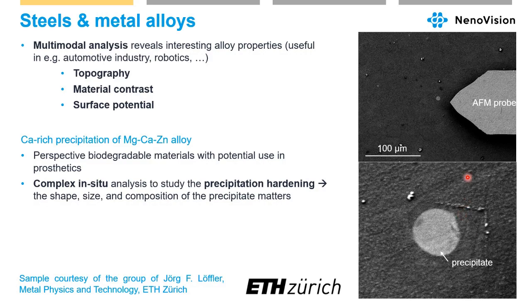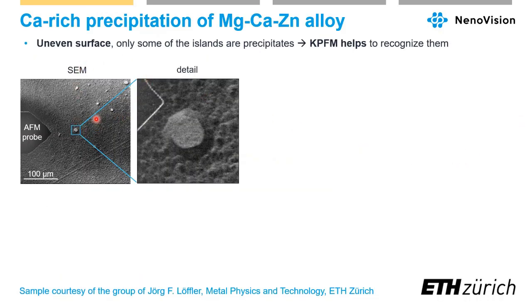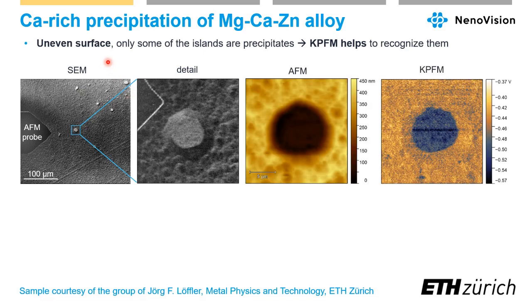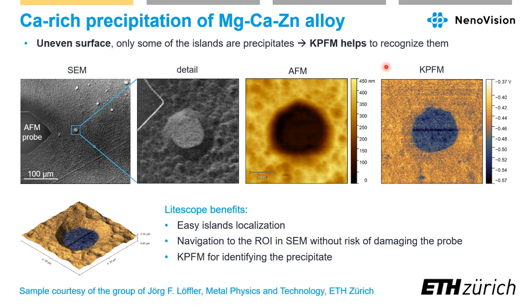So we chose one precipitate. There was quite an uneven surface, so only some of the islands were actually precipitates, even though they looked quite similar. And so the KPFM signal helped us to recognize them because they have quite different potential than the rest of the sample. And so we were able to easily localize the islands and navigate the area of interest in SEM without damaging the probe, because there were quite big particles there as well, and then use KPFM to identify the precipitate.